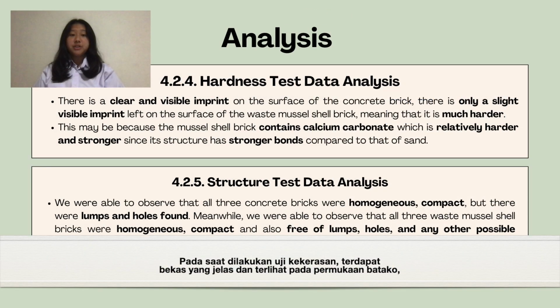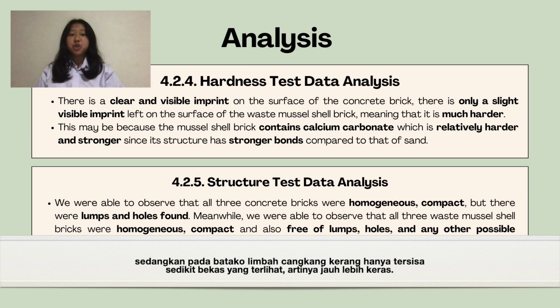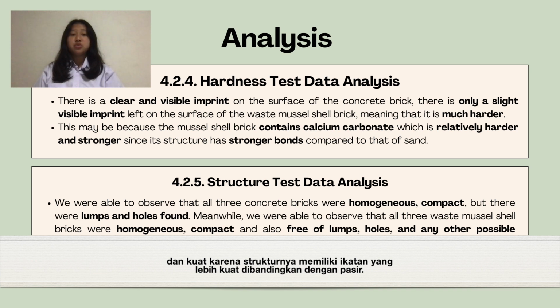When doing the hardness test, there was a clear and visible imprint on the surface of the concrete brick, whereas on the waste mussel shell brick, there is only a slight visible imprint left, meaning that it is much harder. This is due to the brick containing calcium carbonate, which is relatively harder and stronger since its structure has stronger bonds compared to that of sand.